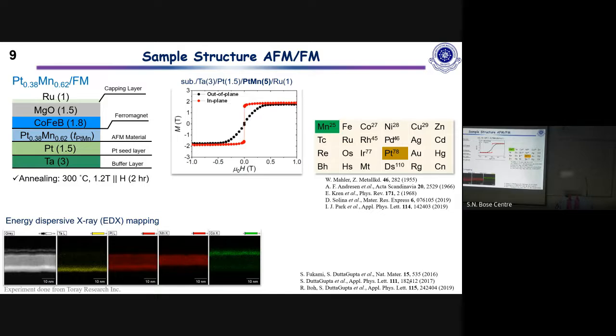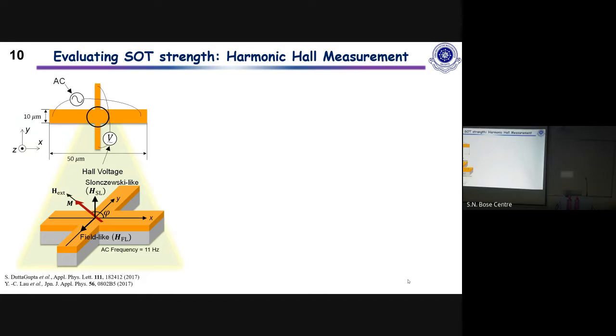So what we wanted to do was, because we have two questions. The first is whether this antiferromagnet is a source of spin Hall effect. That we have to clarify first. So we first tried to investigate the strength of the spin-orbit torque in the system by a technique which is called harmonic Hall measurement. There are actually various kinds of techniques that you can use for the spin-orbit torque quantification, and one of them is called the harmonic Hall measurement.